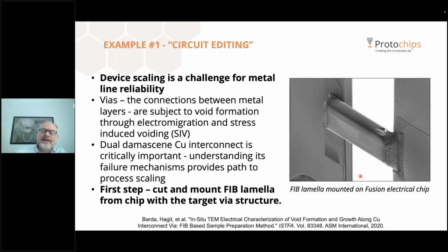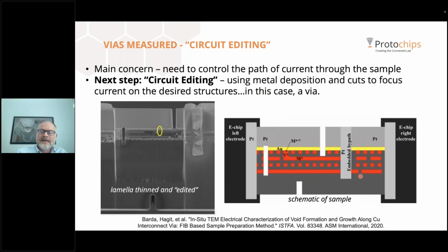So here we have a FIB lamella from a chip that's made with a dual damascene metal process, common in the industry. And we want to isolate a via from the circuit and image it while applying a bias. So the first step is to cut and mount the sample. Now, as we discussed earlier, our main focus is controlling the current path so that the current goes through the sample and only through the sample. So it goes through what we want to see, in this case, a particular via.